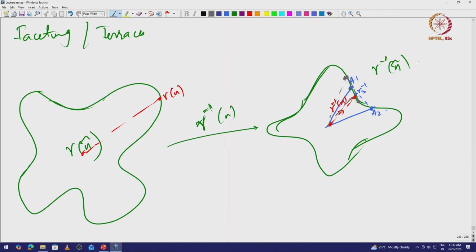So, like that I can start drawing these tangents, which are just straight lines that are going to encompass these points, right. So, between these two tangents I have unstable surfaces, and otherwise these are all stable surfaces, because if I take 2 points here and then I draw a line here, right, this gamma 3 star is actually inside, or gamma 3 is outside.